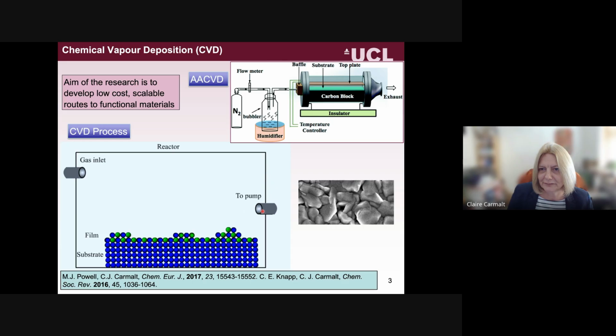Now, it's a really excellent process, but it does have drawbacks, because the precursors have to be volatile enough to get into the gas phase for then the reactions to occur and the thin film to grow. And that obviously limits the number of chemicals that can be used, and often chemicals that are volatile enough tend to be quite pyrophoric or corrosive or toxic. So we changed this slightly and we moved to a solution-based CVD, which is known as aerosol-assisted chemical vapor deposition, or AACVD. And in this case, you take your precursor or precursors and dissolve it in solution. Then you create an aerosol, there's different ways which I'll talk about in a moment. The aerosol is then pushed into the reactor using a carrier gas, such as nitrogen.